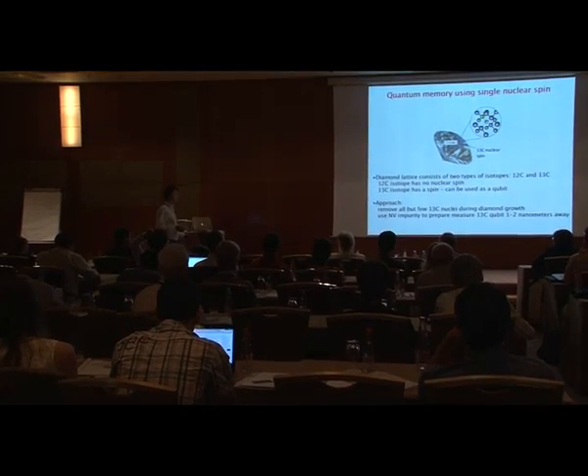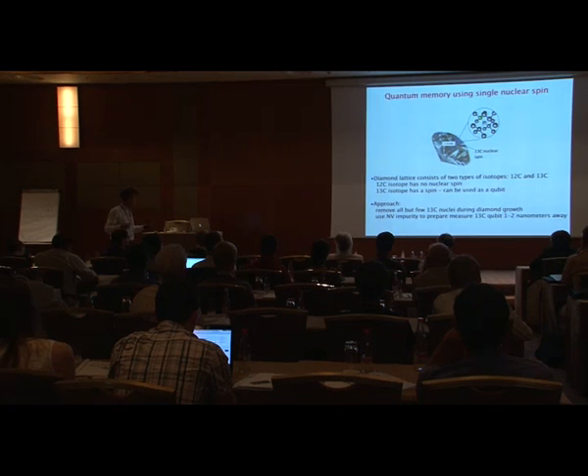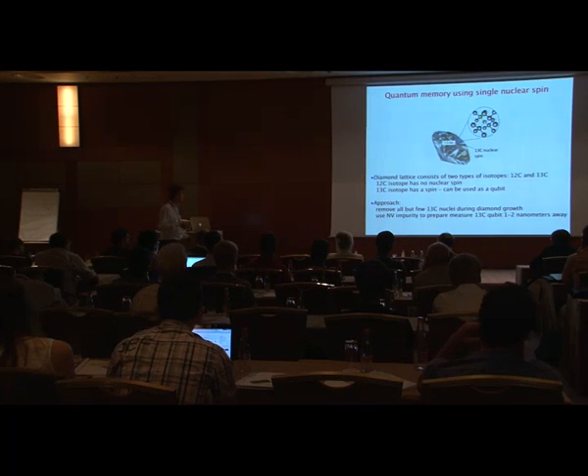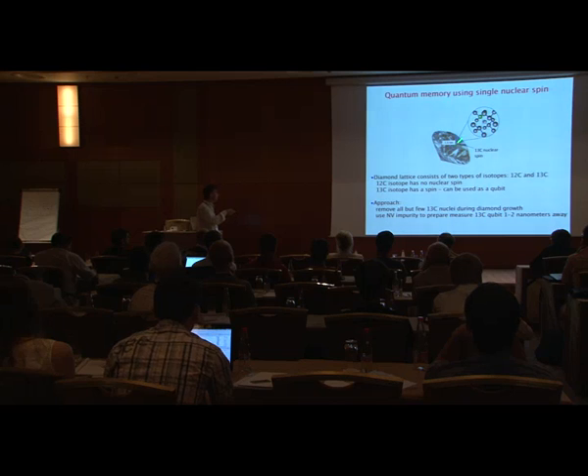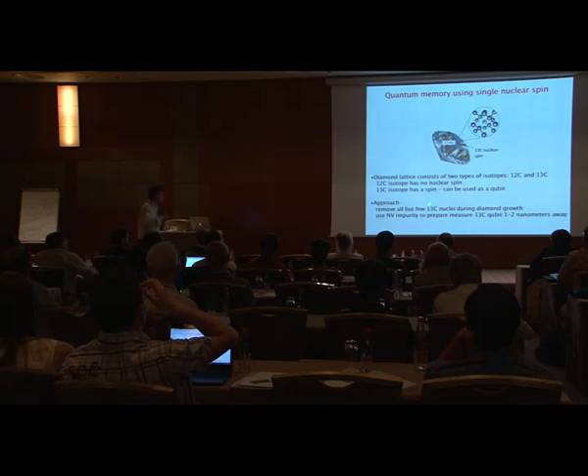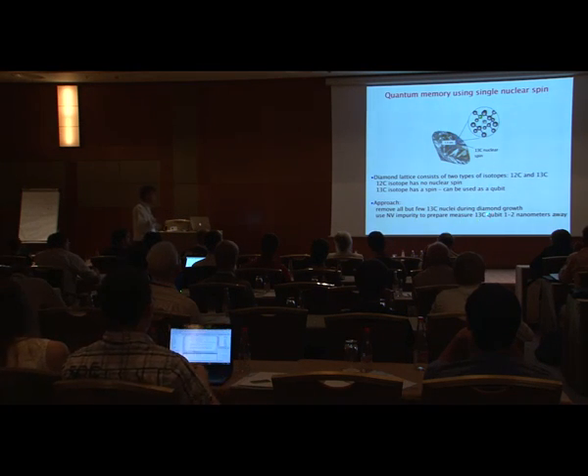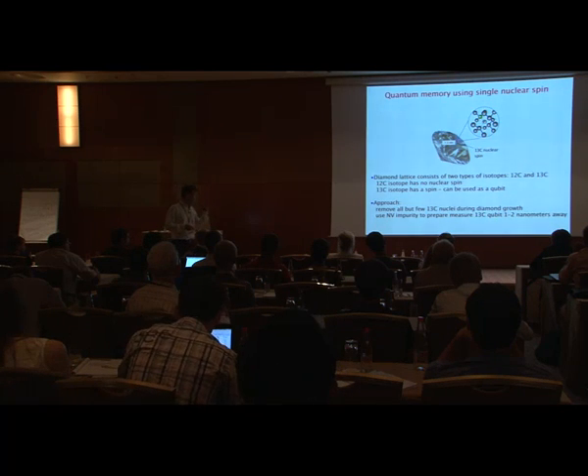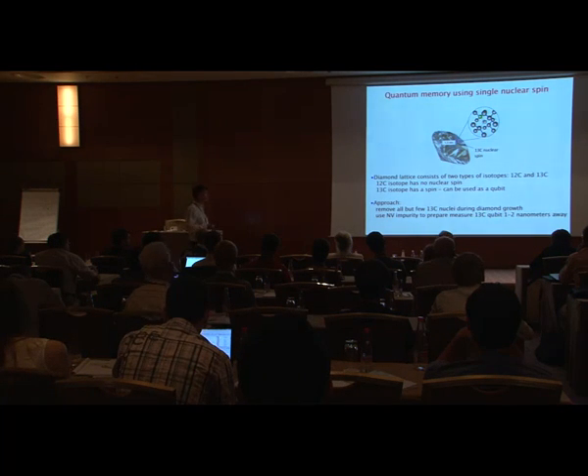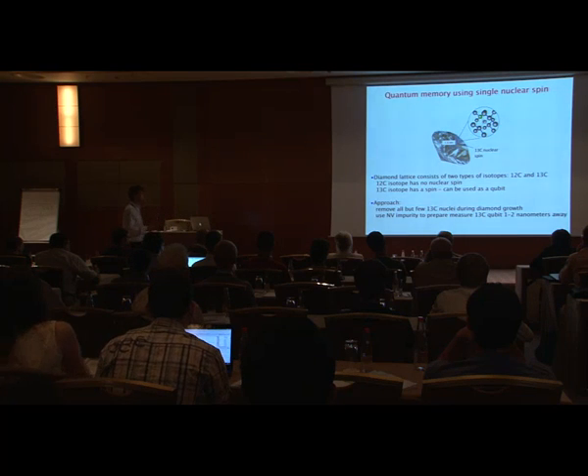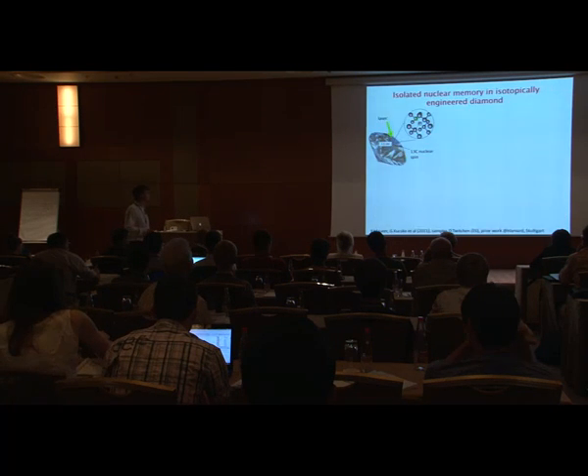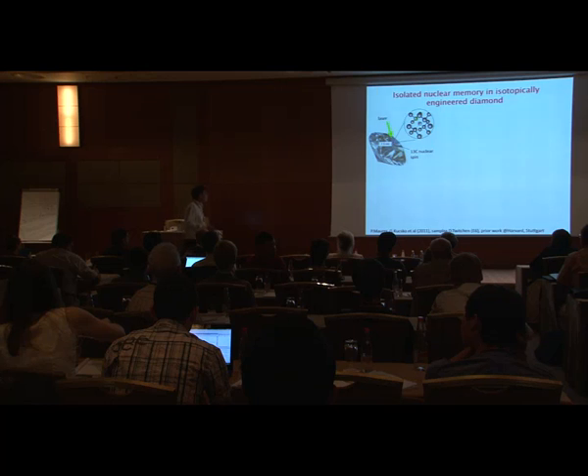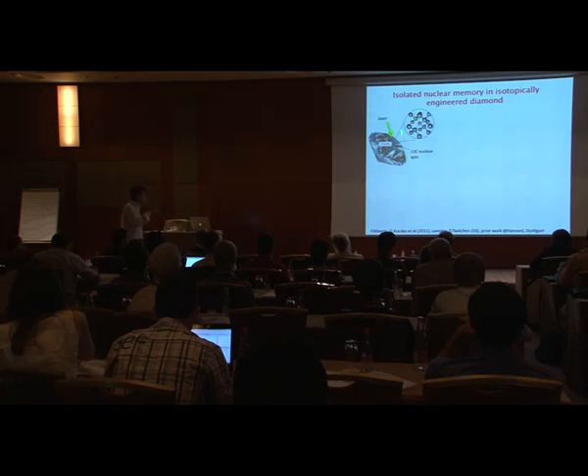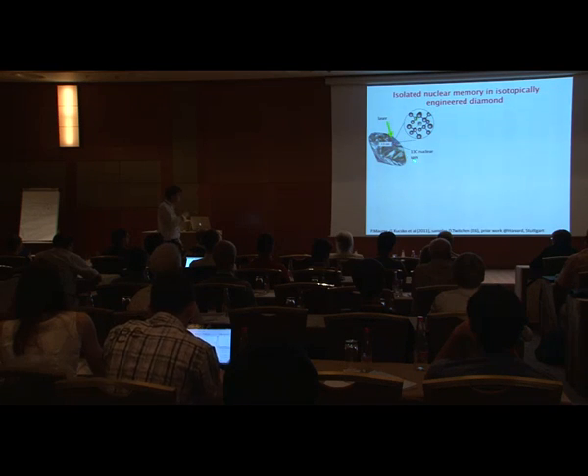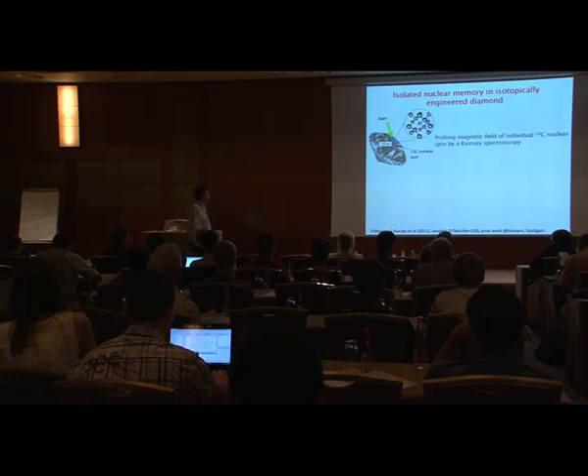And the approach then is basically to remove all but a few carbon-13 nuclei during diamond growth, and then use this impurity, this artificial NV center, to prepare, measure, and manipulate a single nuclear spin, which is actually a few nanometers away from the nitrogen-vacancy impurity. So here is how it's done in practice: you just shine laser light on this impurity, and this impurity is used to sense the single carbon atom.